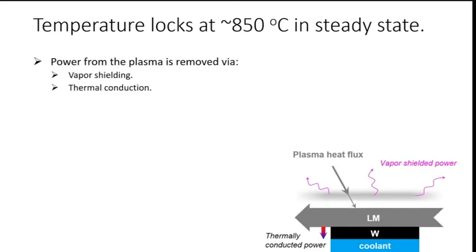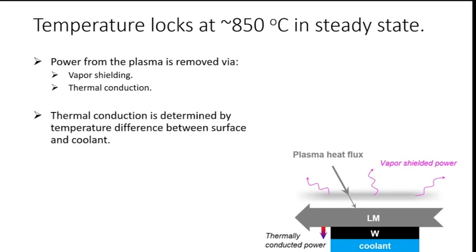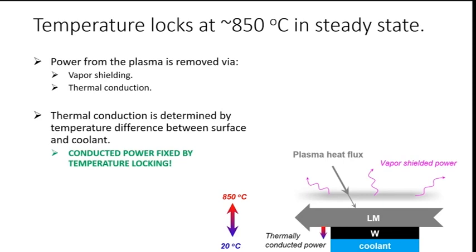And if you wonder how you can estimate that, think like this. So we know there is vapor shielding and on the other hand, thermal conduction. Now, thermal conduction is determined by the temperature difference between the surface and coolant. And we know that the cooling water is at 20 degrees Celsius, at least in Magnum PSI or whatever it is in another setup. And the surface temperature is locked. We find experimentally that it's always locked at 850 degrees. So that means that if this temperature difference is fixed, also the amount of power going to the coolant is fixed.